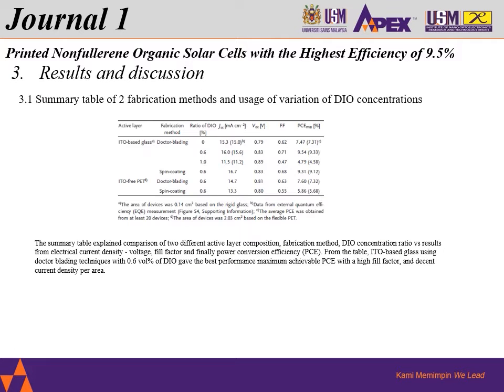So going into the results and discussion of this journal. Over here, I have a summary from the journal itself, in which it talks about the two active layers just now, which are ITO-based glass and also ITO-free PET, with two different fabrication methods, which are doctor blading, which this journal has interest in, and spin coating as reference, and then with various ratios of DIO concentration. So basically, this table summarizes three different variables. What would be the results out of it? The JV measurement was reported out, the fill factor as well as the PCE, the maximum PCE achievable.